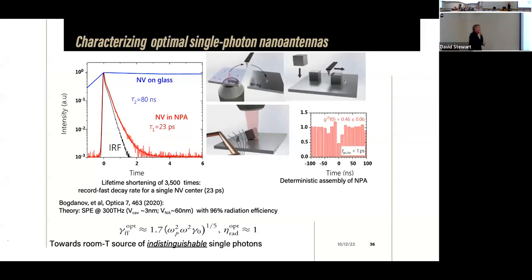So here are our first initial tries. In this case, we just took a nanodiamond with a nitrogen vacancy as a emitter, picked it up with the tip of the AFM, placed it on this epitaxial silver, and then used this tip to push the cube on top of this, so it sits at the edge between the cube and the epitaxial film. What we obtained was a shortening of the lifetime by 3,500, which is very impressive, and that allowed us to obtain a record short lifetime, 23 picoseconds. And g2 does go below 0.5, not much, but still below, indicating that this is a single-photon emitter.